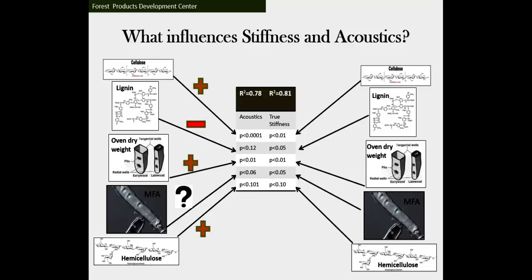So it really does see microfibril angle. And it does see the suite of traits at the same magnitude as what you see here. Then the other thing we found out through the model is it makes sense in terms of how it explains things. Like we would expect cellulose to transmit sound quickly, while we would expect lignin to absorb sound. And that's what the model demonstrated.